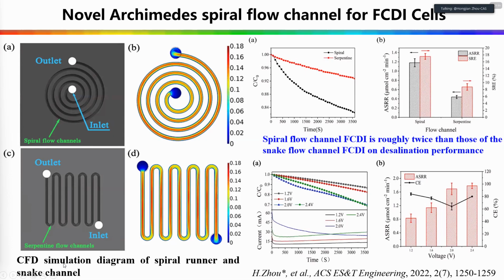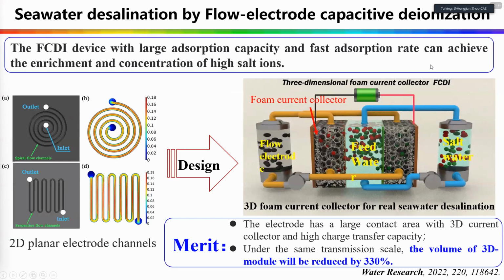Because we did the CFD simulation, we can find in the snake channel, the flow rate is not uniform. In the straight line, the flow speed is fast, but in the corner side, the flow rate is slow. So the whole flow velocity is not uniform. But in our spiral flow channel, the flow rate is uniform. And this is our mechanism and our experiment result. We can find this structure improved performance twice. So okay, I will speed up.